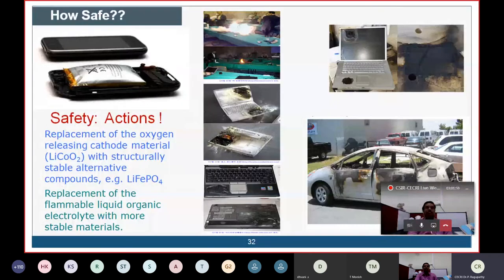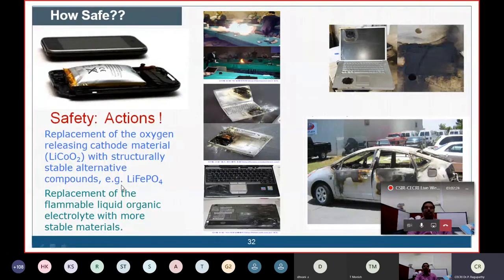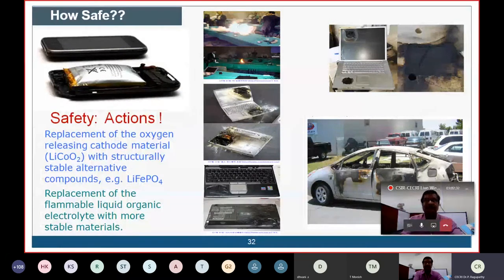You may have heard of lithium-ion explosion incidents. This is due to the oxygen-releasing nature of the lithium cobalt oxide cathode. Though LCO is a good material, there is a safety issue — that's why you need to replace it with alternatives like lithium iron phosphate. The organic-based electrolytes used in lithium-ion batteries are highly flammable and may catch fire.